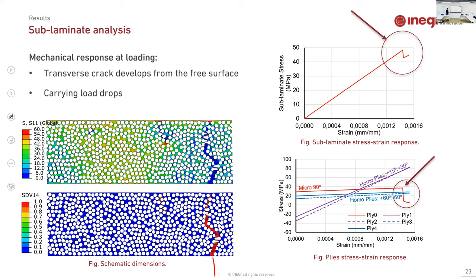But what happened in the complete sublaminate? The complete sublaminate stress-strain response has this behavior. Here we have a small drop of the load because you lost one lamina's load carrying capacity. Okay. But the other layers are still sustaining loads. If we see how each one of the laminas in the sublaminate behaves, we can see that the 15 and 30 degree laminas are still okay, and only the transverse ply that failed has the load drop here. Okay. This is why the transverse fracture is not completely relevant if we see the whole picture, because the load drop is not very important.